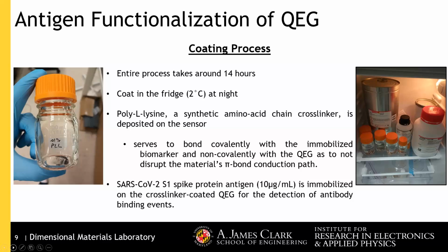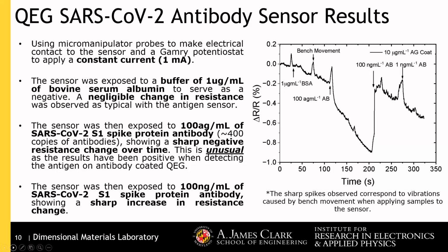Then using 10 micrograms per milliliter was how we used to check antibody binding events. So here's what we got for our results. When we did our last testing, we didn't really get the results that we wanted. You see here, we first started off, the graph is going up. These first movements here are from the bench movement, when we ran our current through, we saw a little spike from physically moving the table. And then we actually started the actual conduction itself. We got a negative graph, which we did not want.